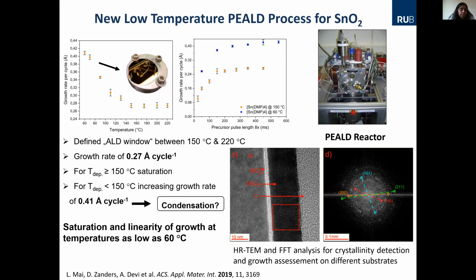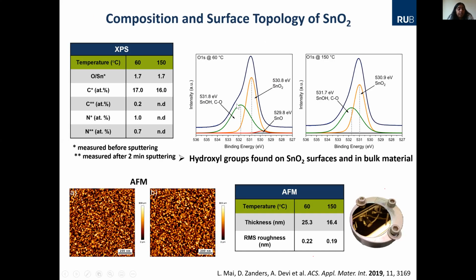And important is that we found that at such thin layers, you have a very good interface between the substrate and the film. It is also confirmed from the TEM analysis. Also, the required phase is formed. And what was also confusing in the beginning: why are we getting a high growth rate at such low temperature? Was it condensation or is it a real film? But we checked, and later on we saw that during the composition analysis.